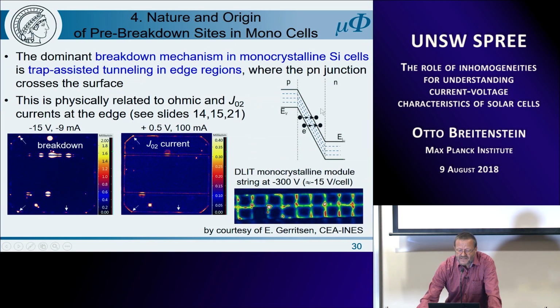And here, this is a nice image of lock-in thermography, which was produced by Eric Gerritsen of CEA INES in France. And it shows a DLIT image of the monocrystalline module string at minus 300 volt, which is also about 15 volts per cell. And you see the breakdown occurs only in the edge region. This is very different to multicrystalline material.